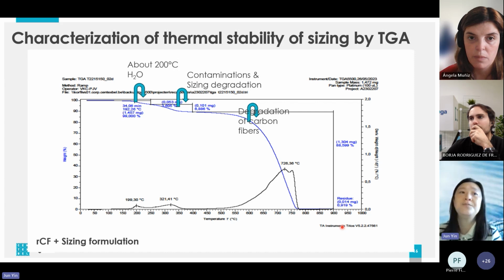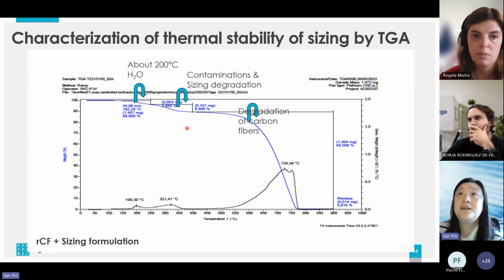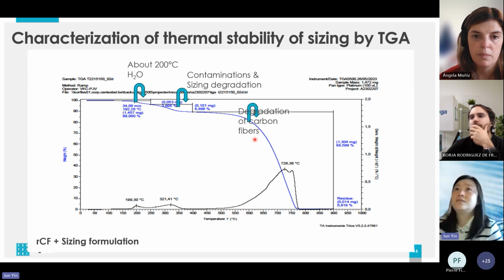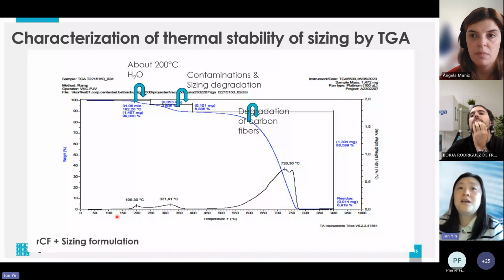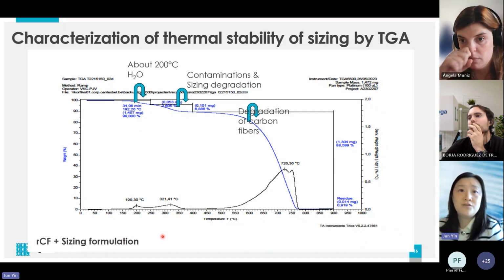the sizing by TGA. So we can see on this curve, with the temperature increasing up to about 900 degrees, there are 3 stages. The first stage is about 200 degrees. The water starts to evaporate. And the second stage is the contamination of the surface, and the sizing starts to be degraded. Then the third stage is the carbon fibers start to be degraded. So that means the sizing formulation is still stable at 200 degrees.